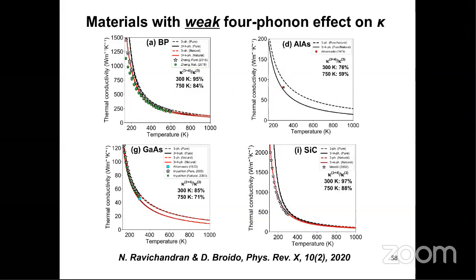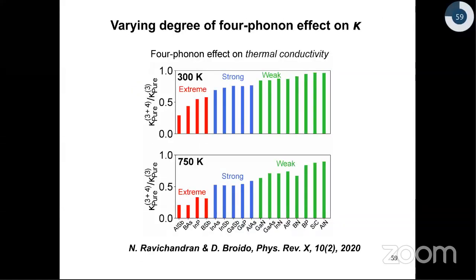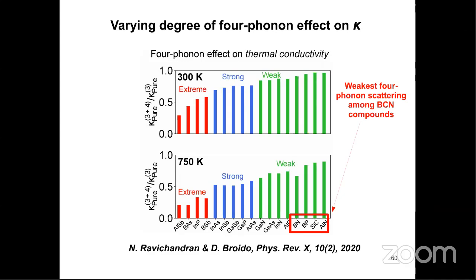But there are also materials where the effect of 4-phonon scattering is weak. We do find some of the III-5 compounds like boron phosphide, gallium arsenide, and silicon carbide, where the dashed and the solid lines are roughly overlapping or very close together, indicating that 3-phonon scattering, the conventional picture, is sufficient to describe thermal transport in these materials. To give you a consolidated picture, I'm plotting a histogram of the effect of 4-phonon scattering, that is K3+4 divided by K3. You can see at room temperature, all the III-5 compounds with the green bars have a very weak 4-phonon scattering, and there are a few candidates, including boron arsenide, which have extreme 4-phonon effect. Interestingly, we find that the candidates towards the right side, where the 4-phonon effect is weak, include BCN compounds. What I mean by that is these compounds are composed of boron, carbon, and nitrogen and some other atom.